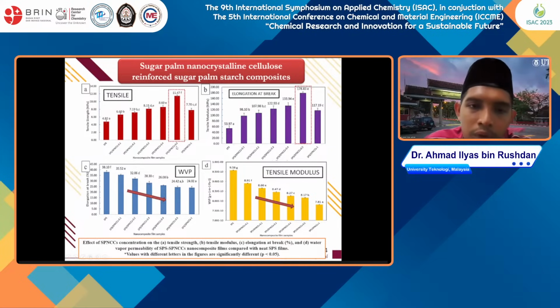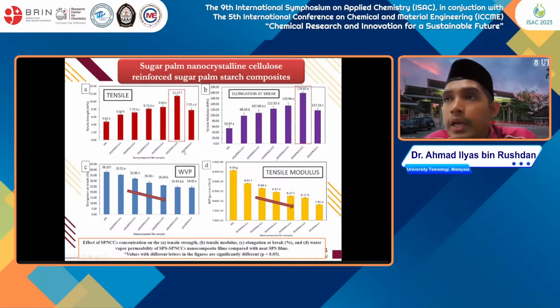tensile strength. This was with only 0.5 loading included, and it can increase up to 11.47. This is due to the bonding formed between the nanocellulose and the starch.